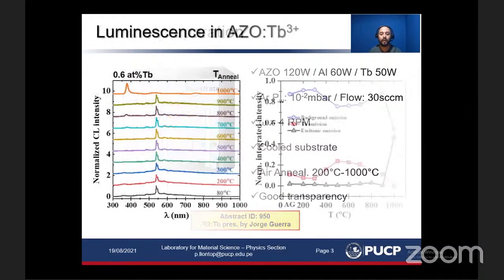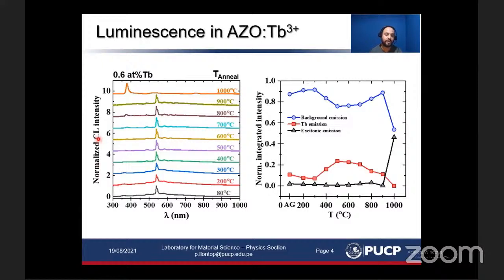Okay, so here the figure on the left shows the normalized cathodoluminescence intensity versus the wavelength. Here is the spectrum for each annealing temperature, for this sample with this terbium concentration. And as you can see, we obtained the characteristic emission for terbium. Okay. And to further analyze this, we divided the spectrum area into three parts.